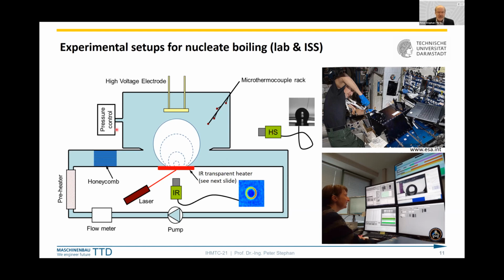We have a high-speed camera to observe the shape of the bubble, and we have a microthermocouple rack with different tips, very small microthermocouples of less than 50 micrometer diameter, to measure the temperature at different positions in the two-phase fluid, both inside and outside the bubble in the thermal boundary layer.